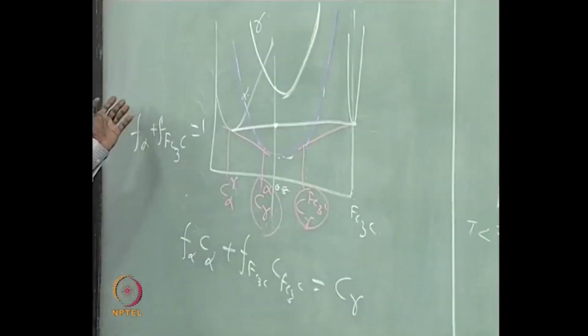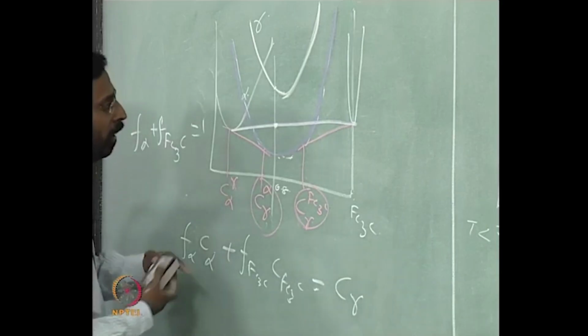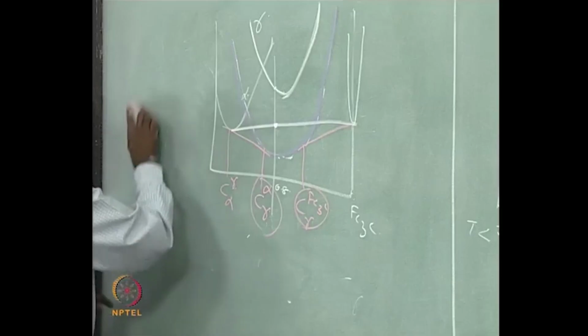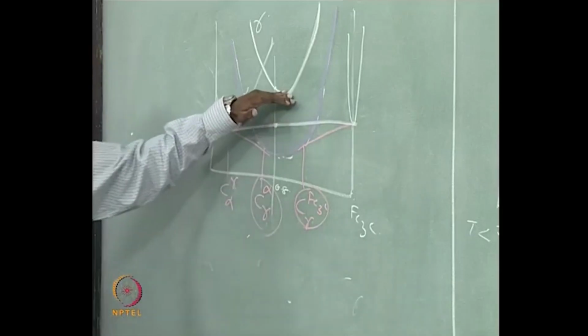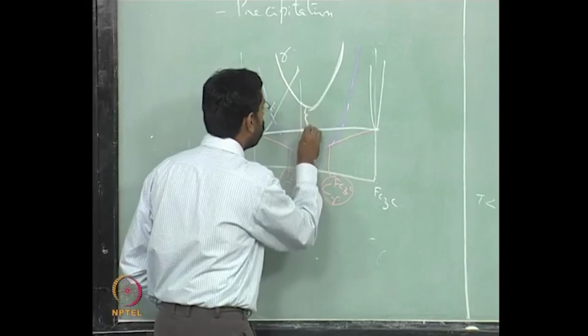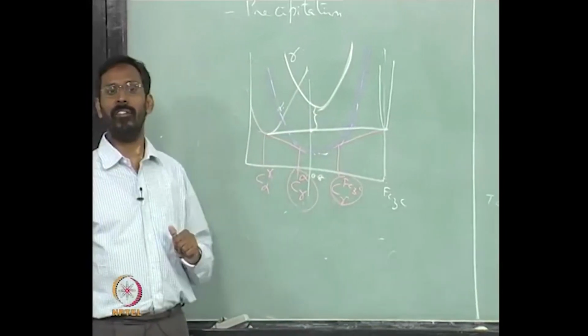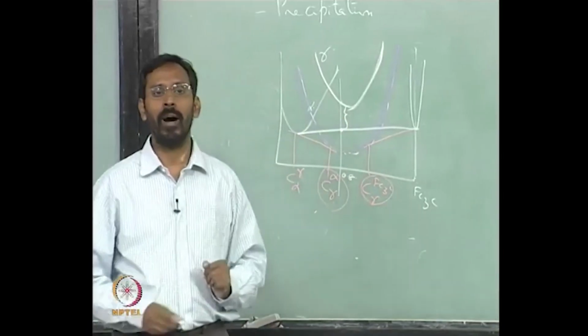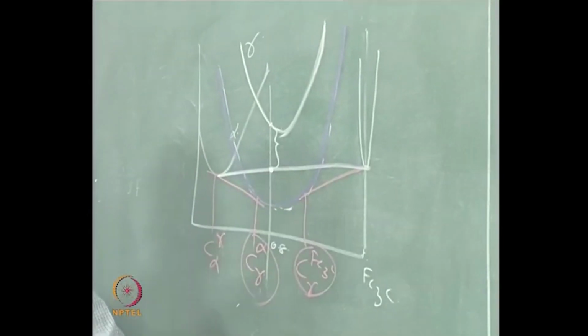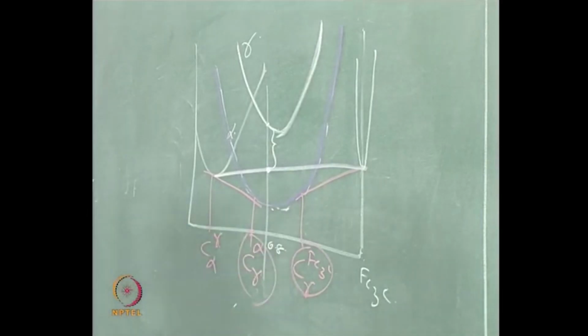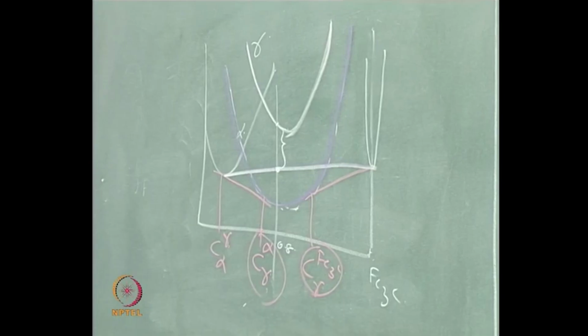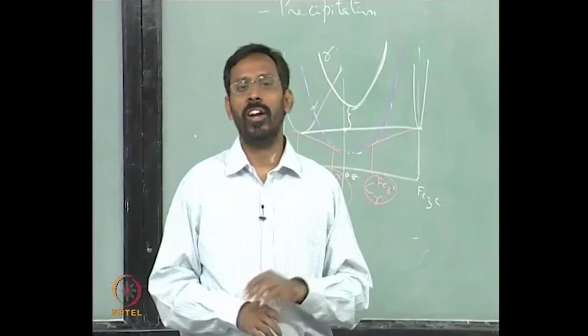Whichever phase that we are talking about, here we talk about alpha and cementite, you can call it alpha beta, you can call it alpha gamma, anything that you call it. So, the same equation, and for liquid to solid also we use the same thing, okay. So, this is what you see, that the moment I come to a temperature which is below that, now you have a situation here. So, there is a driving force, and because there is a driving force, gamma does not want to remain as gamma, it wants to precipitate alpha plus Fe3C. The question now we are talking about is what happens, how does this initiate? The gamma wants to transform, how does this transformation get initiated?